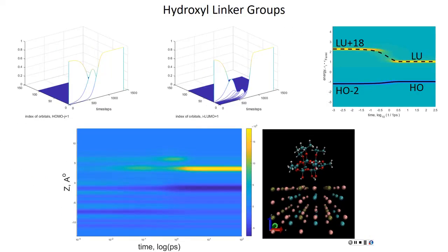How is it different from the previous one? Can you go through it? This one isn't as localized on the perovskite. You've got a little bit of your electron density on the titanium dioxide to begin with here. So it's not really a complete charge transfer, I guess it's a little bit of hybridization with your quantum dot or whatever it is. And it looks like you get into a more charge-separated state earlier than in the previous case, because this one hits that by the 100 femtosecond mark.